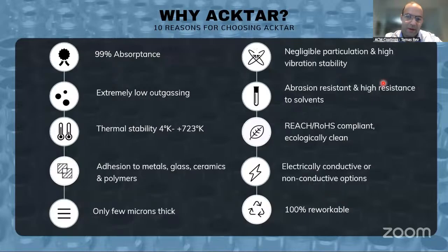So why do customers come to us? I'll give you 10 reasons why. Basically, as I mentioned, our coatings are black coatings. I'm talking about black, 99% absorbing in a very wide broadband range of the electromagnetic spectrum. They are extremely low outgassing. In fact, ESA has chosen us as a reference material on the EMA mission to the International Space Station. Our coatings are thermally stable, so between minus 269 degrees Celsius and 450 degrees Celsius, they are completely qualified.